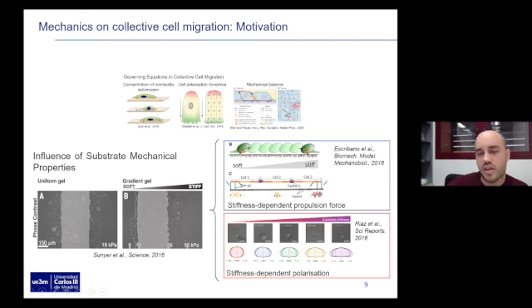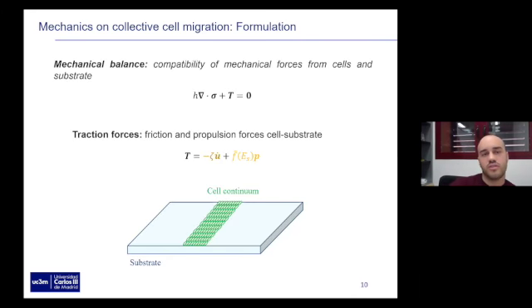But if we look at some experimental works in the literature, we realize that this is not only this propulsion force, but also somehow a stiffness-dependent polarization. So we can observe that this cellular polarization depends on both the magnitude of the substrate stiffness, but also on stiffness gradients. So at this stage, we wanted to provide a simple modeling framework to test these different hypotheses and determine from a mechanical point of view what is the implication of each one. So we started with the mechanical balance.